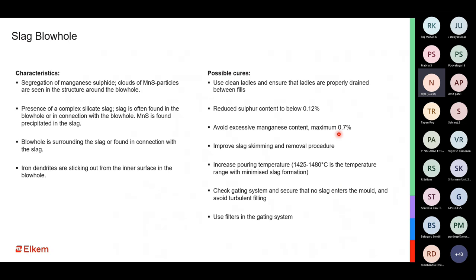We have been through this. We have seen the characteristics of a slag blowhole as such: segregation of manganese sulfide, a cloud of manganese sulfide particles which can be visible around the blowhole. Of course, it will always be connected to the actual slag which is present inside the casting, so it can be traced into the slag inclusion whenever we have a slag blowhole in the system. How do we resolve it?